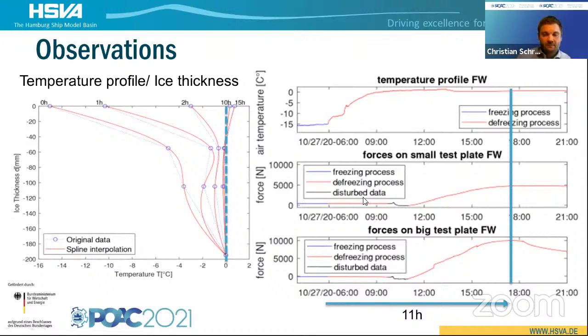I agree. What we also found is that most of the forces occurred in the last degrees. It might be a reason, but from the conclusions on the temperature change to the forces, we could see that the highest force level or the highest increase was in the last 2 or 3 degrees, from -3 probably to almost 0. There was the biggest force expansion level, you can call it.